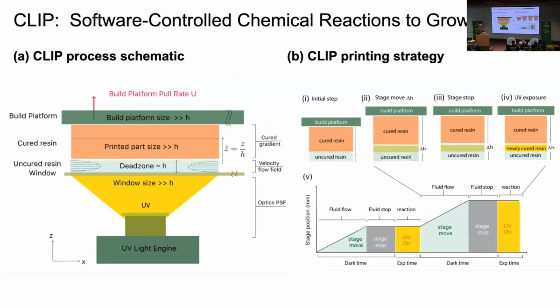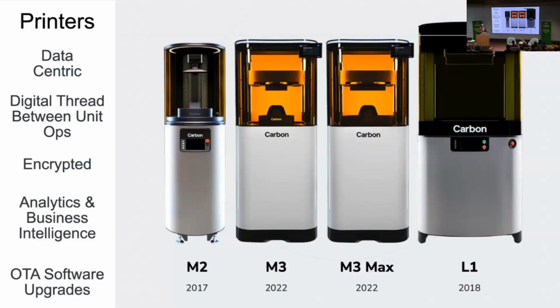Because what's happening is you have the fluid flowing in laterally, you have the part adhered to the platform, and with the printer, we can control every aspect. So we can lift up the platform off to the next increment. We can wait for the fluid to stop flowing, and then we can illuminate. So it looked like a movie, but it's flashing quickly, okay? And every step of the process we control exquisitely. And so we developed a printer, and in the beginning, it was really hard to tame. So we wanted to have a printer that could evolve over time. So we used a subdiscipline of mechatronics, meaning that every aspect of the printer is remotely controllable with software.